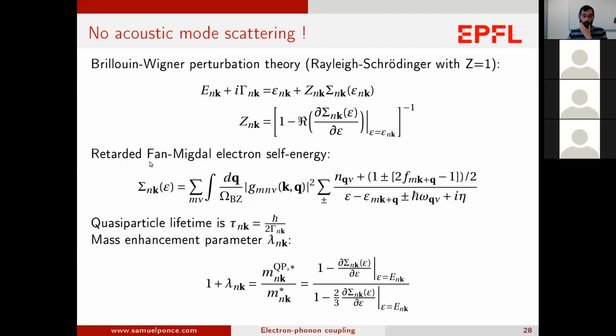And so I'm coming back now to this Migdal electron-phonon self-energy, which is nothing but this g times those factors. So this looks very similar to the scattering rate that I have shown before. And indeed, the imaginary part of this is the scattering rate. And the reason I'm showing this is that the mass enhancement parameter can be shown to be 1 plus this mass enhancement. And this is the ratio between the effective mass and the bare effective mass. So the quasi-particle effective mass and the bare one. And this can be shown to be the ratio between this self-energy evaluated at the renormalized eigenstate.